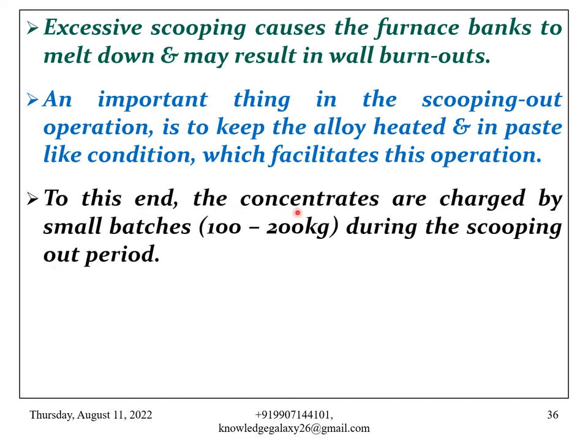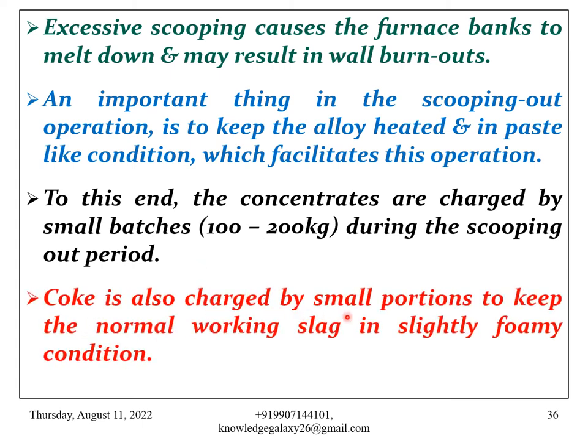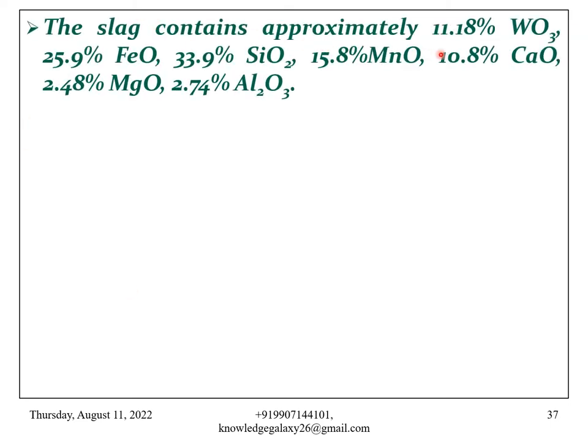To this end, the concentrates are charged in small batches, that is 100 to 200 kg, during the scooping out period. Coke is also charged in small portions to keep the normal working slag in a slightly foamy condition. The slag contains approximately 11.18% WO3, 25.9% FeO, 33.9% SiO2, 15.8% MnO, 10.8% CaO, 2.48% MgO, and 2.74% Al2O3.